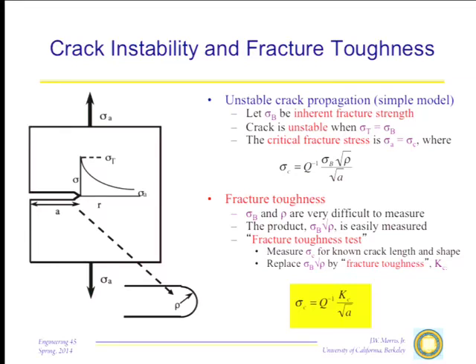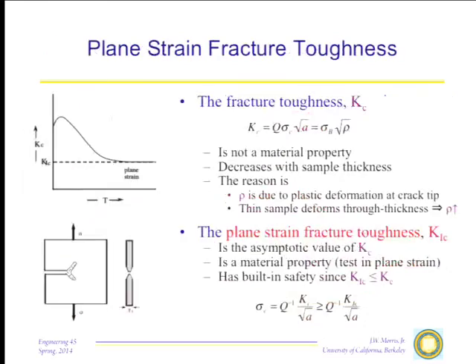The problem I have, it's only half a problem for reasons I will not tell you, is that this fracture toughness is not yet a material property. And the reason it isn't is that the fracture toughness depends on the geometry of the sample that I'm testing. Suppose I take a sample and crack it, load it up, there'll be some plastic deformation usually here at the crack tip, and I take samples of various thickness, and I measure the fracture toughness as a function of the thickness of the sample. What I'll find is that the fracture toughness depends on the thickness of the sample, and the dependence looks something like this. There's some fuzziness here at the beginning, but then the fracture toughness drops off monotonically as the sample becomes thicker until it asymptotes to a value K1C, which is called the plane strain fracture toughness.